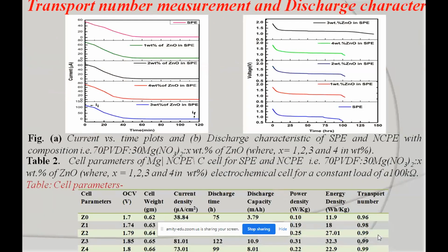Now, transport number measurement and discharge characteristic. The first figure represents the current versus time plot, and from this curve, we will calculate the transport number for our electrolyte system. We got the transport number for our systems in the range of 0.96 to 0.99. And 0.99, which is close to 1, represents that our electrolyte is purely ionic in nature. All transport number values are represented in the table given below.